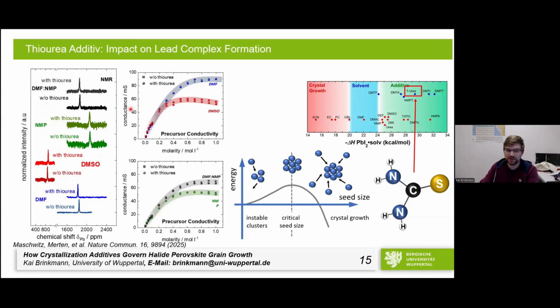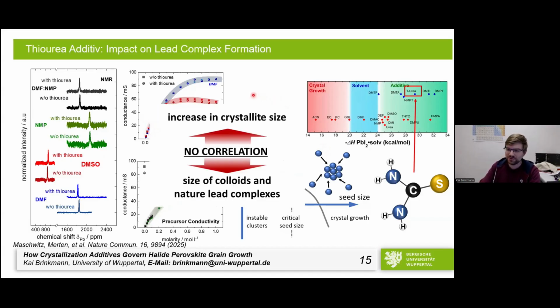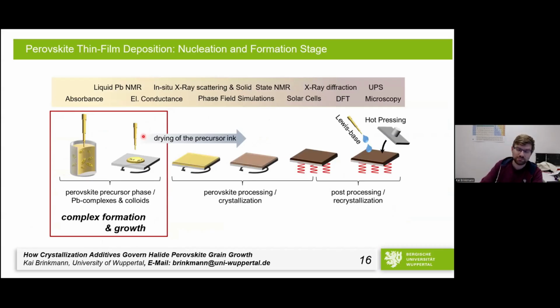And then we did the conductivity measurements, and the same results. So basically, it was impossible to disentangle what we got with and without the thiourea by either of these two methods, which made us a bit confused, because this was literally what we were thinking about, right? The whole hypothesis that we're talking about basically depended on the amount of colloids, the size of colloids, and what we see depending on what happens in the solution. So far, we don't see any correlation between the size of the colloids, the nature of the lead complexes, and the increase of the crystal size in the end. And this, well, I told you, was very frustrating. So that was basically the first year of our journey.